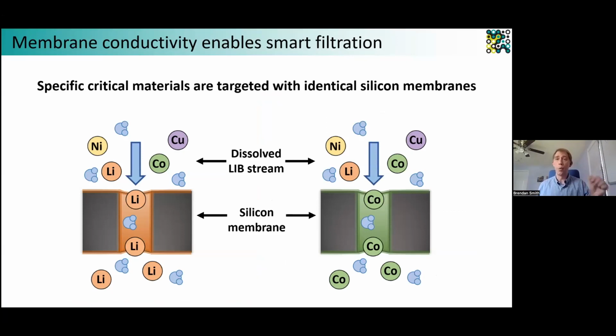So for instance, we turn the knob once, we allow lithium to flow through the membrane, and we achieve a pure lithium solution on the other side. We turn the knob again, and this time we're actually extracting cobalt from solution in a very selective way. So this is a drastic simplification of how it actually works, and I can take some questions on that if there's interest. But generally, we have this ultra-versatile membrane that can target a broad number of critical materials from very complex and very harsh solutions coming in.